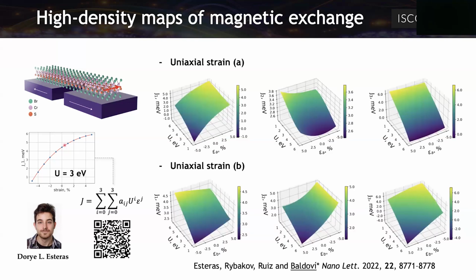So we started, in this case, Dorje was performing calculations taking a single chromium sulfur bromide monolayer and doing uniaxial strain along the A direction, along the B direction. And in this case, keeping, for example, Hubbard U constant, we can observe the trend of one magnetic interaction. So we were also varying the Hubbard U in all the calculations and the different factors of strain and fitting using the least squares method to have these high density maps of how an exchange interaction is evolving with U and